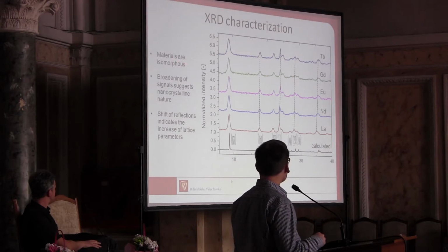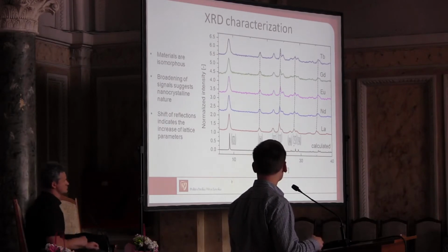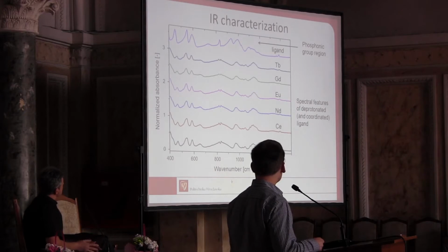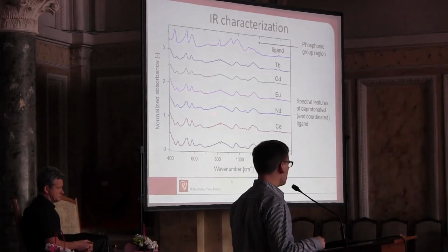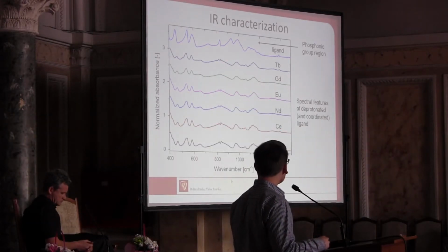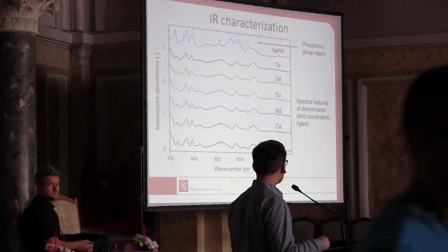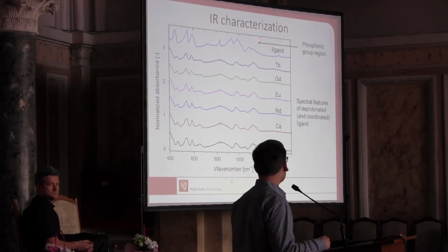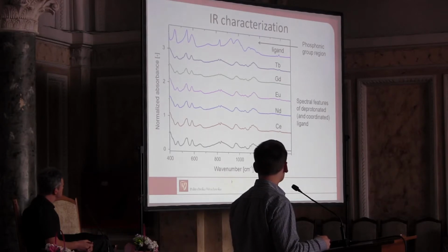And indeed, the materials are isomorphous and correspond to the earlier described phase. The same conclusion can be drawn from the IR characterization, since the spectra between materials are very similar. Here, for comparison, the spectrum of the phosphonic ligand is provided, and we can see that the main spectral change is the lack of the phosphoryl group stretching vibration.